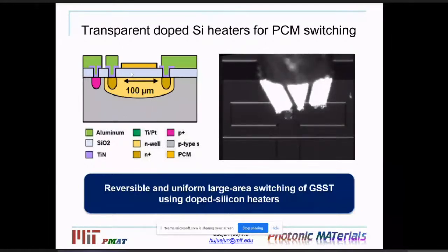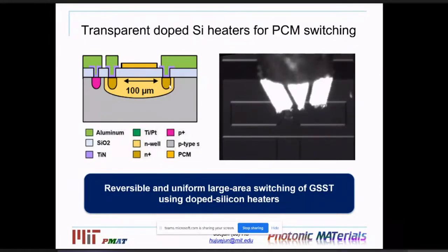In this schematic, I'm actually missing one layer on top. I should have corrected the figure. Every time we put on these phase changing materials, we always cap them with a capping layer. Usually it's ALD aluminum oxide, or sometimes we also use PECVD silica, just to prevent any kind of oxidation reactions. So you definitely need to cap that to prevent any oxidation reactions.